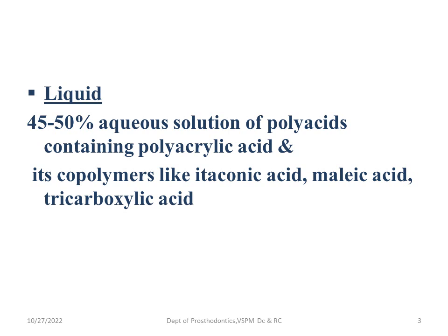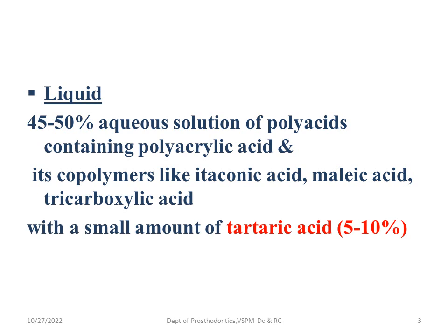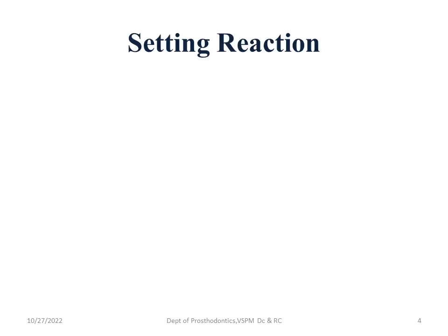This liquid component also decreases the viscosity of the liquid and the tendency to undergo thickening by gelation due to intermolecular hydrogen bonding. One more component, a small amount of tartaric acid, is also added, around 5 to 10%, which has a role of increasing working time, decreasing setting time and preventing the thickening of the liquid during storage.